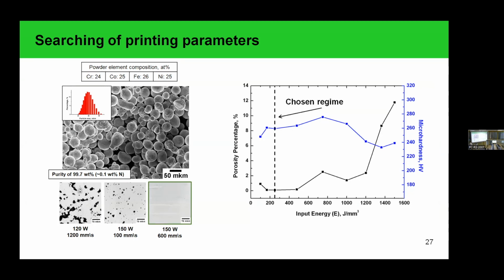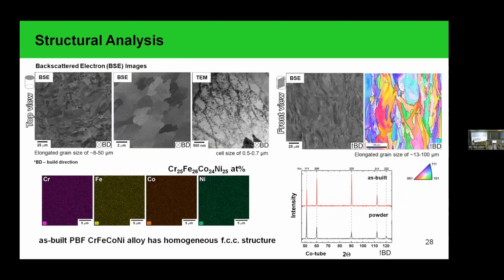We prepared a set of samples where we varied the laser power and laser speed. Based on the results of the porosity and microhardness, we chose one regime and continued work for these materials mostly with this set of parameters. The structural analysis revealed the typical face-centered cubic structure for these materials. It has elongated grains with a size of about 50 microns on the longer side, which relates to the laser spot diameter and the distance between the laser tracks. Also, we observed a cellular substructure with a size of about 0.5 or 0.7 micrometers.